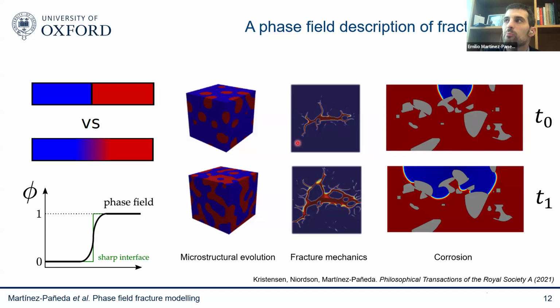And again, this is the output of a simulation. This you can see is a hydraulic fracture problem. You can see very complicated cracking patterns, crack branching, coalescence of multiple cracks, nucleation of secondary cracks. Predicting this kind of phenomena with other methods was very difficult, if not impossible. So phase field has really opened new horizons. But this is only one element of its success. There are three aspects that I think are critical to its success.